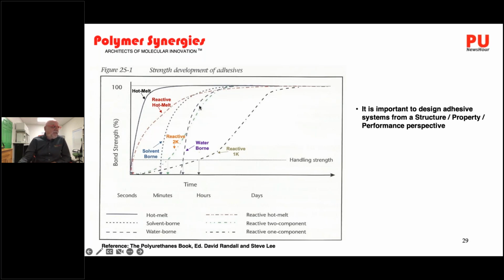You have solvent-borne adhesives, which are going to be faster than water-borne adhesives, because organic solvents volatilize much quicker than water does. In two-component adhesives, we have to build molecular weight by the polyurethane reaction, forming our polyurethane polymer, and that takes time before it builds strength. And it's even slower for one-component material. So these are aspects of polyurethane formulation and development that have to be thought about. And the structure of the polyol and the isocyanate in your formulation is important in the development of these strengths.